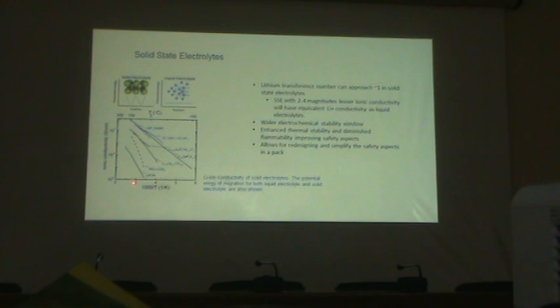If there is an ion conductivity versus temperature plot, it basically follows the Arrhenius equation, and you can see a comparison between all the solid state electrolytes and also the liquid ones here. At the current state, there are certain compounds which have been reported, like LGPS, that is lithium germanium phosphorus sulfide, which can attain this, where the axis is inverse of temperature, 1000 by T.